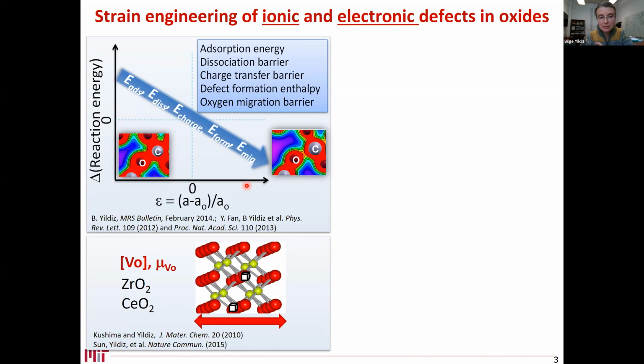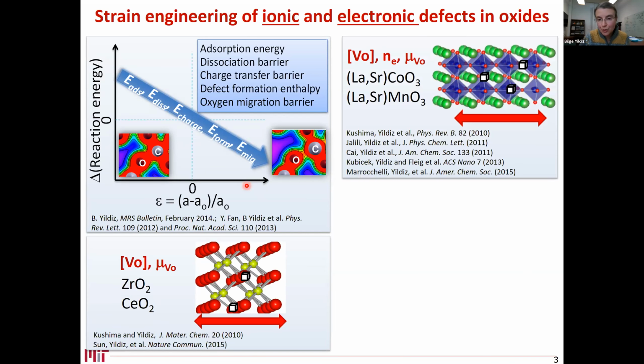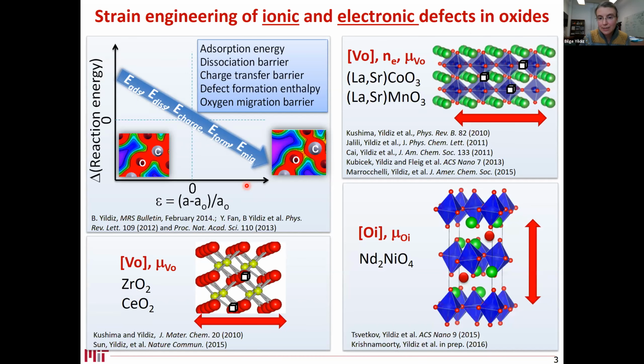And we have studied this in a number of different classes of oxide, binary oxides, ternary oxides such as perovskite oxides, as well as derivatives of these perovskite oxides. So short point again, that oxygen defects under elastic strains respond positively in terms of their formation, mobility, charge transfer ease when we expand the lattice.